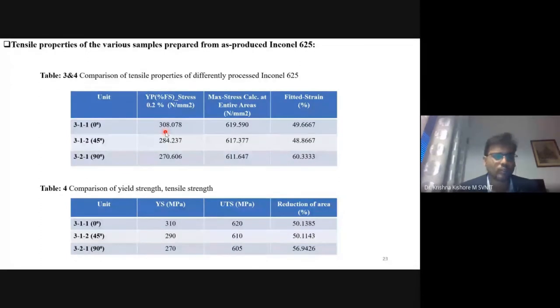But because of our deposition strategies and controlled cooling rates, we can see that at 0 degrees it's about 310 megapascal, at 45 degrees about 290 megapascal, and at 90 degrees almost 270 megapascal, and it's almost quite matching. But still we need to achieve equal properties, and we are having different